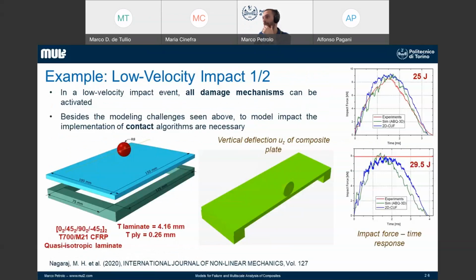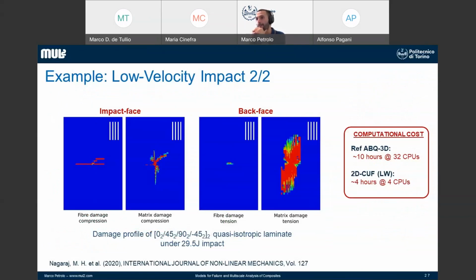So this is the low velocity impact in a plate. You have an impactor, this red ball, that simulates the low velocity impact that you may have in service. This is a typical incident that you can have during the life of your composite components. And the typical results that you can get from a virtual platform are the time history of the impact force, like this on the right. But even more important is the damage distribution. So in this slide, you can see how the damage propagates due to the low velocity impact.